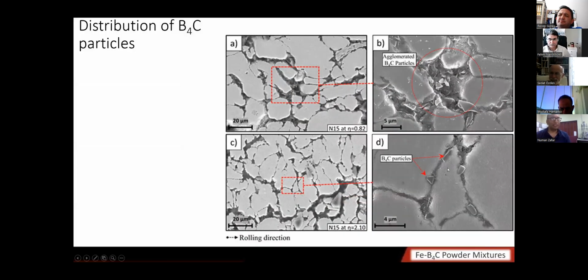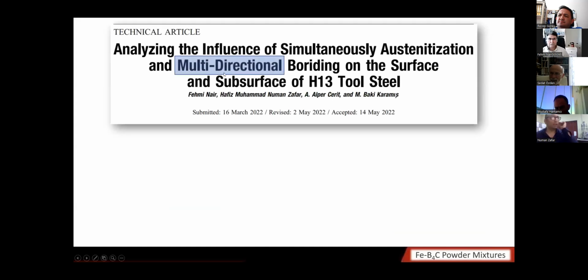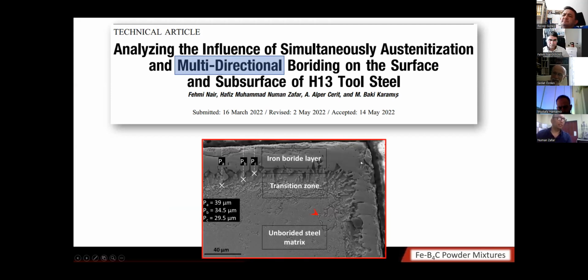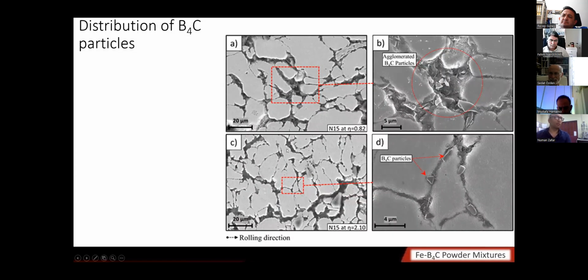But I can see that this iron particle is surrounded by iron boride particles. And this iron particle is surrounded by B4C particles. And in this condition, this particle is going to be subjected to boriding from multiple directions. In our previous paper, we have shown the aspects of multidirectional boriding on the iron. And these regions are the ones which were in contact with the iron powder from two different directions. So there were iron borides formed. So we can believe that the iron borides will also form on the iron particles. They will overlap and there will not be any geometrical discontinuity on the iron particles after the boriding. So we are safe with this type of microstructure, I want to say.